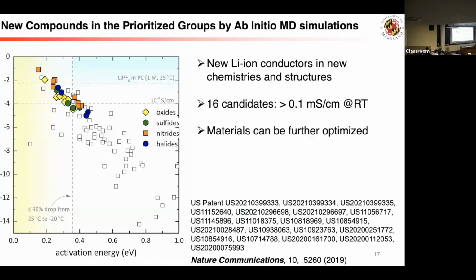The y-axis is the room temperature conductivity, the value I showed earlier, in log scale, and the x-axis is activation energy. So we want the conductivity to be high and activation energy to be low, so we want the material to be in the upper left corner. Among all these materials in the group, we find 16 of them have larger than 10 to the minus 3 room temperature conductivity. You can see they are all highly concentrated in the upper left corner. The open squares are the materials we knew ionic conductivity for before, and they are much more sporadic, with lower conductivity and high activation energy.